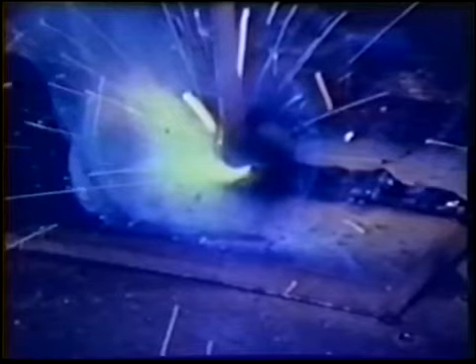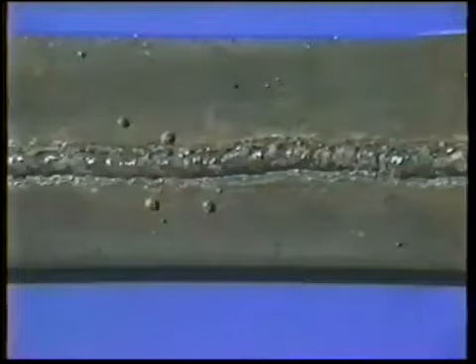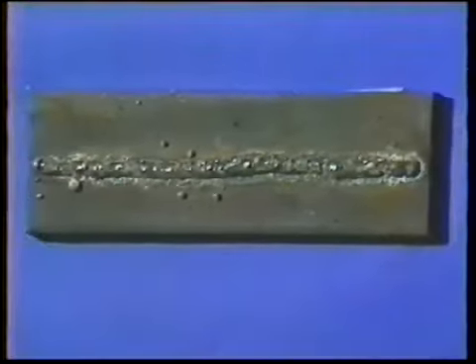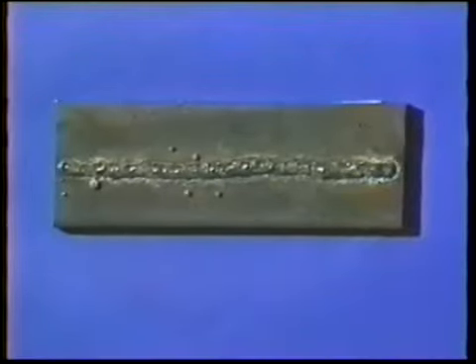If the electrode is operated below the designated amperage range, there is insufficient heat to melt the base metal, and the molten pool will be too small for proper control. The droplets forming on the end of the electrode may bridge to the weld pool, periodically extinguishing the arc. The weld deposit will be irregular and piled up with poor fusion.